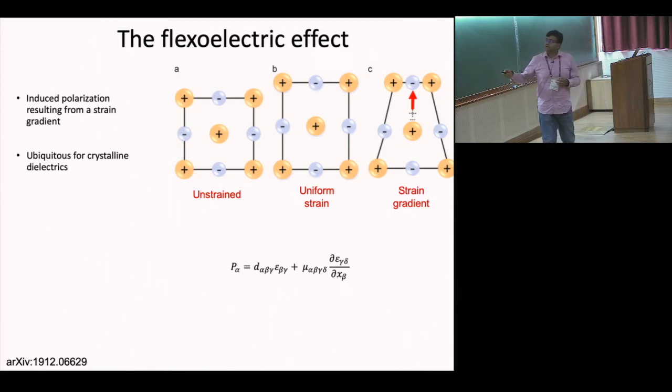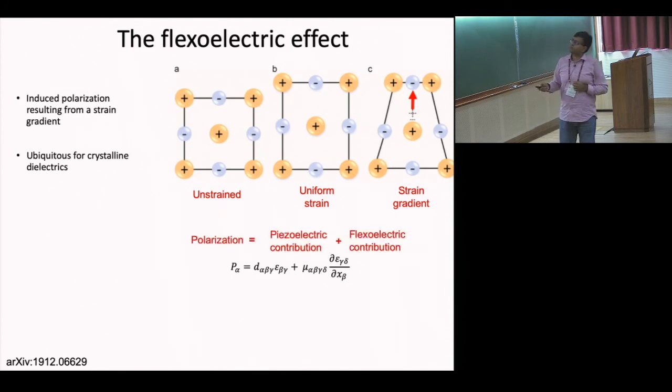This effect, called the flexoelectric effect, is always present, but usually it's swamped by the leading order term, which is the piezoelectric term. These materials are beautiful cases where the piezoelectric term by symmetry is absolutely zero, but the flexoelectric term is non-zero exactly at these domain boundaries.